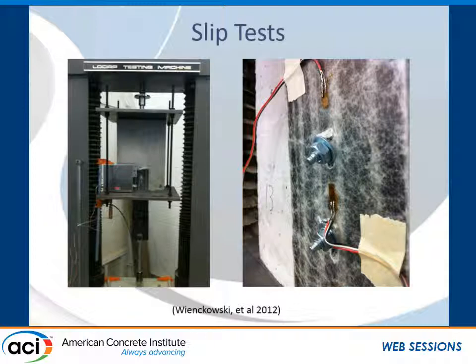Now, our bearing slip model was developed from test data that we obtained from a series of slip tests. The FRP material that we used in all slip tests was Safe Strip. That's a pre-cured laminate of carbon and glass fibers developed by Strongwell specifically for MF-FRP applications, which means that it does have the bearing strength necessary to support the load transfer through the anchor bolts. Fasteners we looked at were anchor bolts. We considered anchor bolts from two different manufacturers in both 6.35 and 9.525 millimeter diameters. That's 1/4 and 3/8 inch anchor bolts, which are typical of the sizes we use in this type of application, and we did consider varying bolt patterns and spacings. Normal weight concrete with 28-day compressive strengths ranging from 27.5 to 55 megapascals, that's 4 to 8 ksi, was used in our tests.